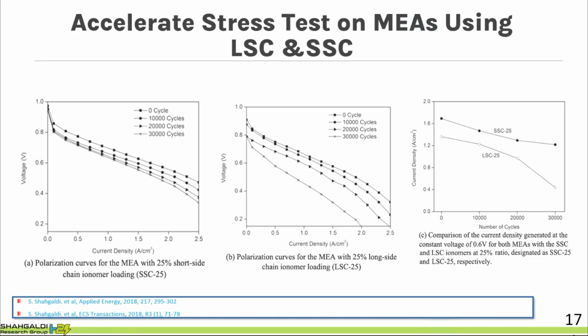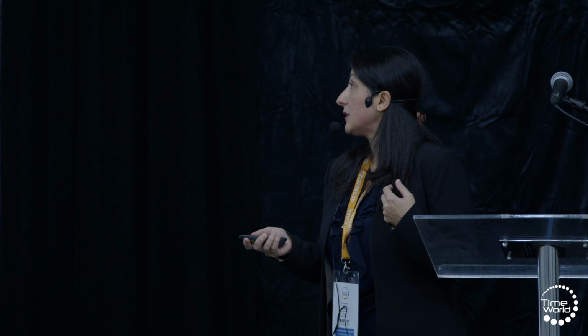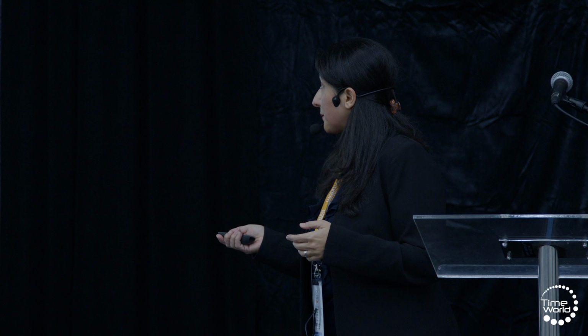So it's not just the catalyst, where we need to put a lot of platinum on the cell in order to have better durability, but also the type of the ionomer that we are using. So we did 30,000 cycles of MEA inside the 50 centimeter square cell based on the DOE script, and we found that the shorter side chain ionomer gives us a better performance compared to the longer side chain. Not only better performance, but also better durability.